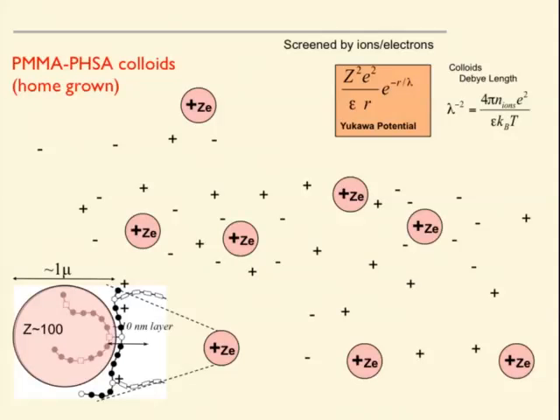Okay, so this is charge neutral. If I say these guys are charged, what I mean is they're charged, but the counter charge is in solution around them. That gives you a screened Coulomb interaction. It gives you a Yukawa potential over here. And this is exactly the same thing you get in a metal. The only difference in a metal is you don't talk about ions, you talk about the concentration of electrons. And instead of talking about temperature here, you talk about the Fermi temperature. And this is Thomas-Fermi screening. And here it's the same thing, except you have kT disordering you, and it's ions here rather than electrons. But it's a screened Coulomb interaction here, just like you would have between charges in a metal.